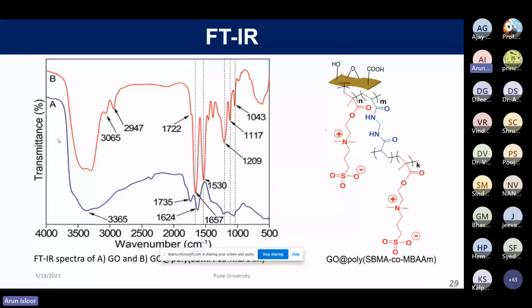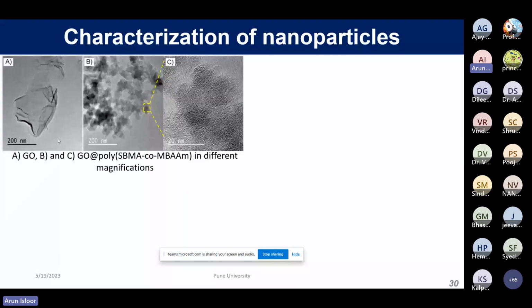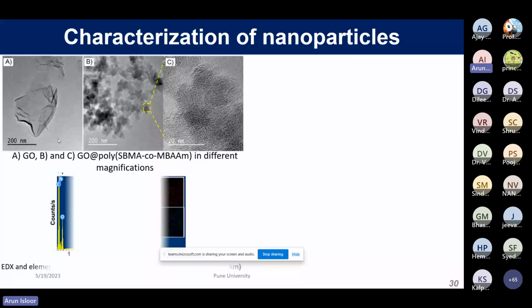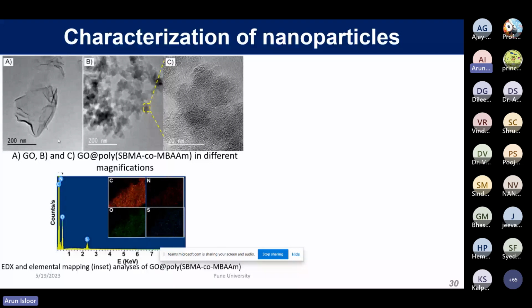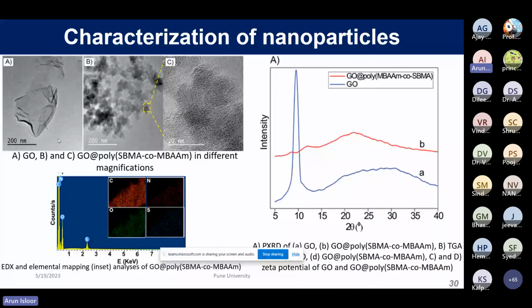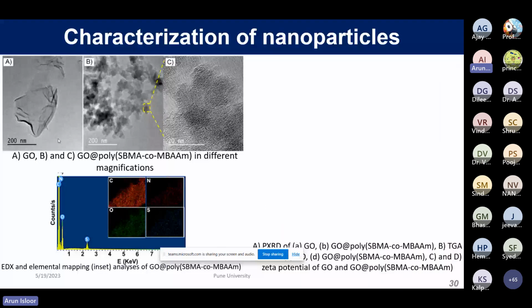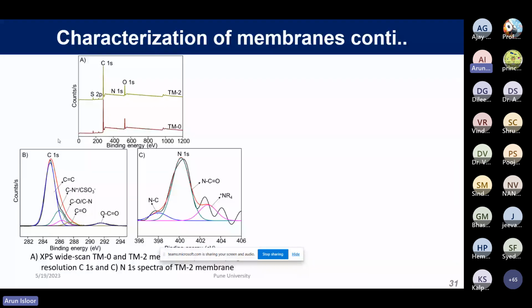Then of course the required characterizations were done, including the FTIR, which confirmed the formation of GO modified by zwitterionic polymer nanoparticles. The TEM was also carried out, and also the EDAX, which again showed the presence of carbon, nitrogen, oxygen as well as sulfur in the elemental mapping. And then the PXRD pattern again showed somewhat crystalline nature. And the XPS has again confirmed the type of bondings present in this novel material.